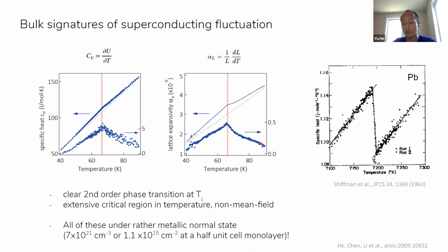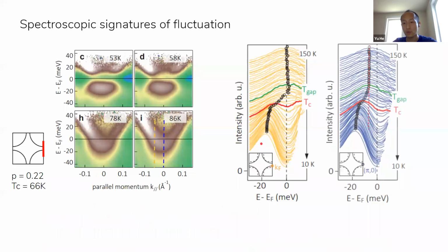Chimiao, to answer your question, in the presence of fluctuating superconductivity, there will be diamagnetism, but the diamagnetism will not be directly proportional to the gap, but it will be proportional to the superfluid density. Because in order to form the diamagnetism, you have to actually have global phase coherence to some extent to form those diamagnetic currents. That's why above TC, even though there can be preformed Cooper pairs, the diamagnetic response is disproportionately weaker than what you would get in the bulk superconducting state.